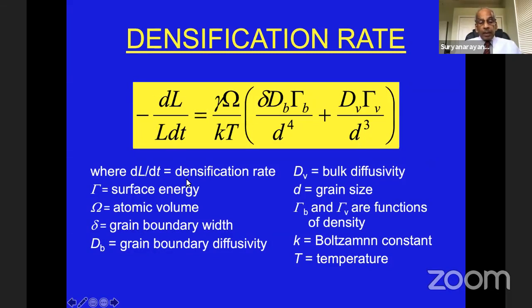This represents the densification rate. So if D decreases, the densification rate increases, or if the diffusivity of either the volume or the grain boundary increases, this densification rate also increases. But in the case of nanocrystalline materials, the diffusivity is higher and the grain size is smaller. As a result of this combination, the densification or consolidation of nanocrystalline materials is very easy, and that is an advantage for nanocrystalline materials.